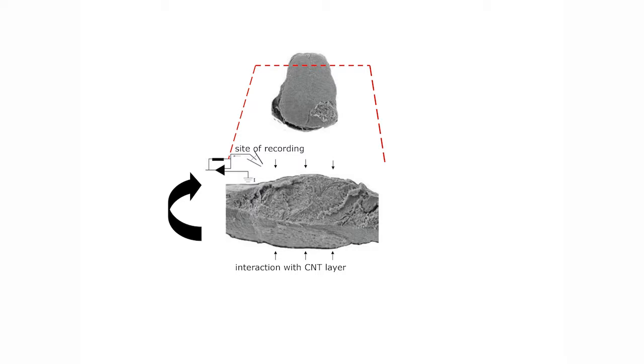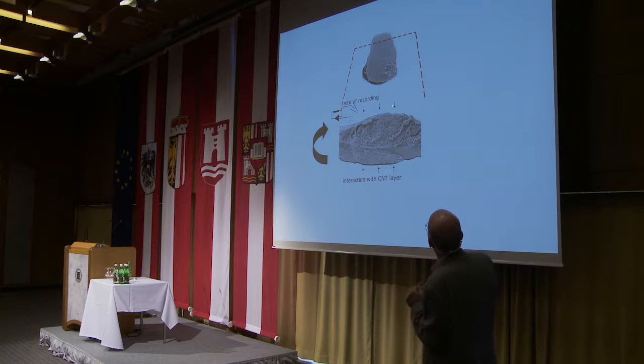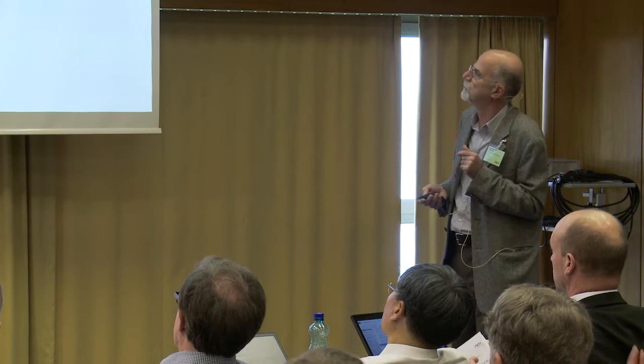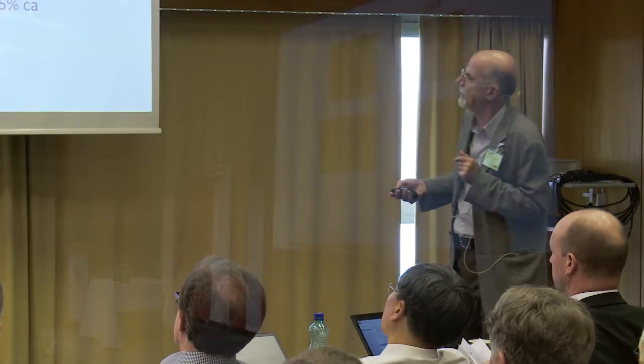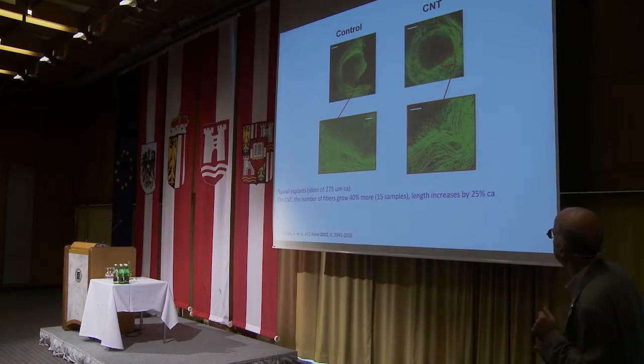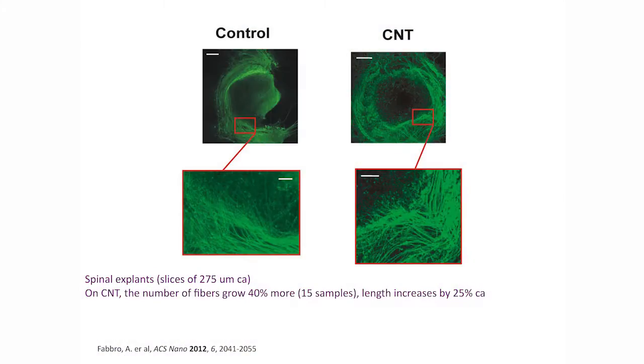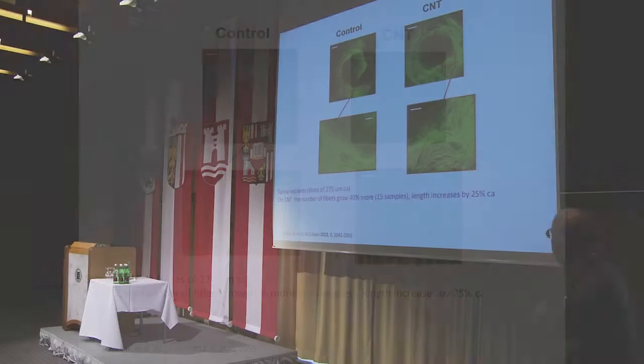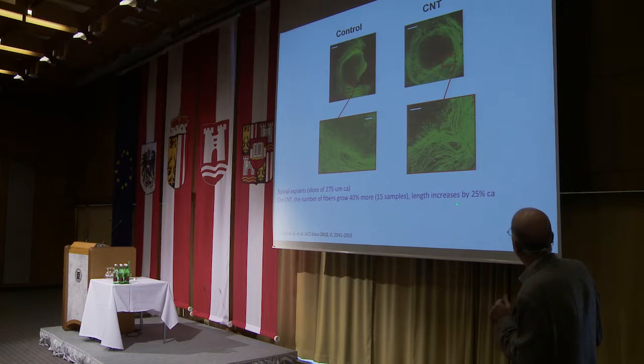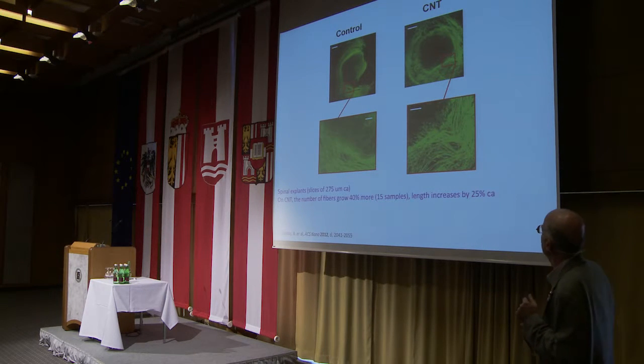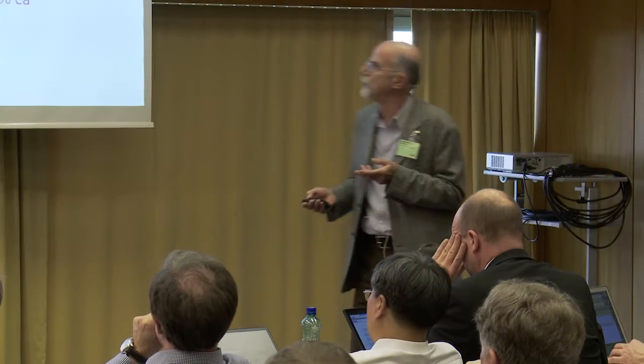So here we have the interaction of the carbon nanotube layer, and on top we take the recording. This is a slice of 275 microns in thickness. And basically what we find is that on carbon nanotubes, the number of fibers grows 40% more. So the fibers are much denser in number, but also the length increases by 25%.